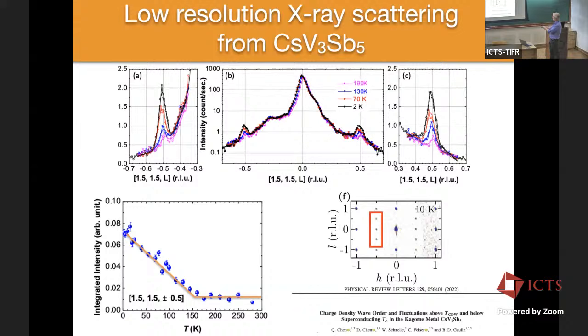So this is a scan. This would be in the HHL direction rather than the H direction, but we would be doing a line scan that would go through the series of peaks that you would get as a function of L, with peaks at 1/2, 0, and -1/2, right? So 1/2, 0, and -1/2. But you can see that we're not necessarily seeing very well-defined Bragg spots, as you see here. We're actually seeing a streak that goes up and down here, and that has considerable structure in it, right? It's really peaked at 0.